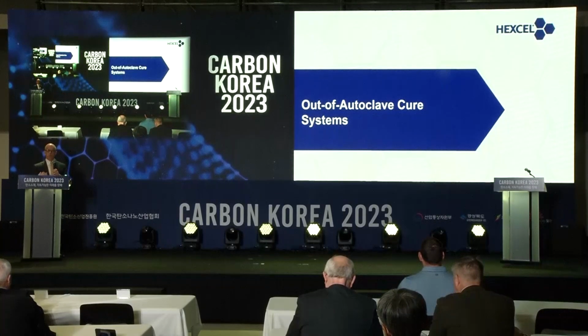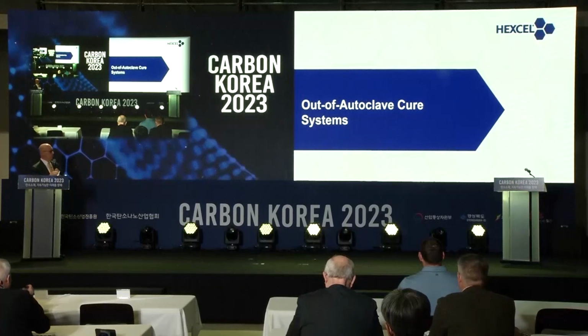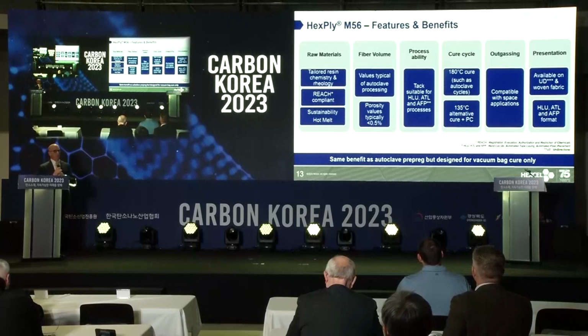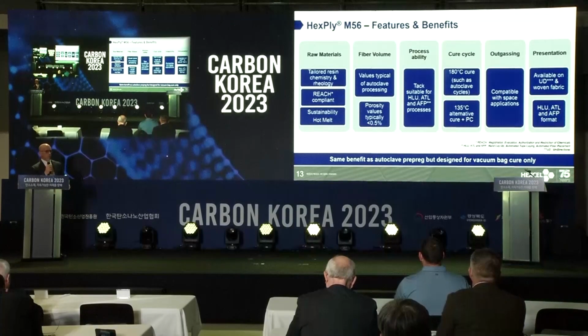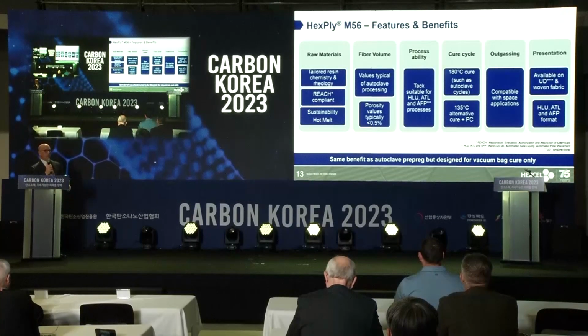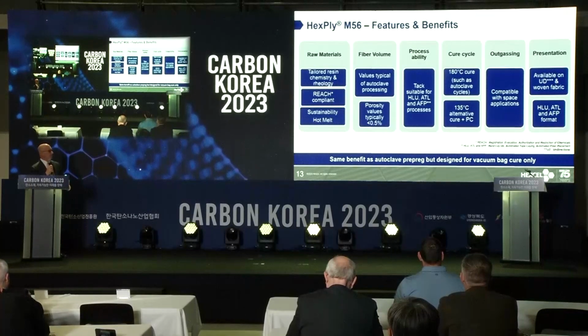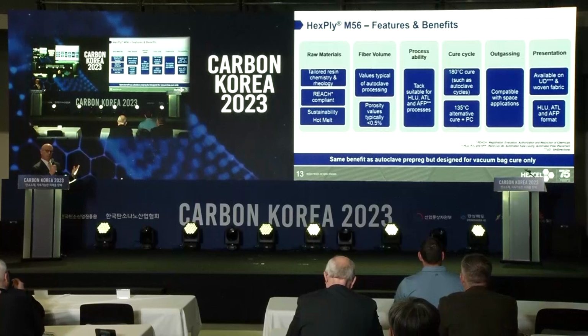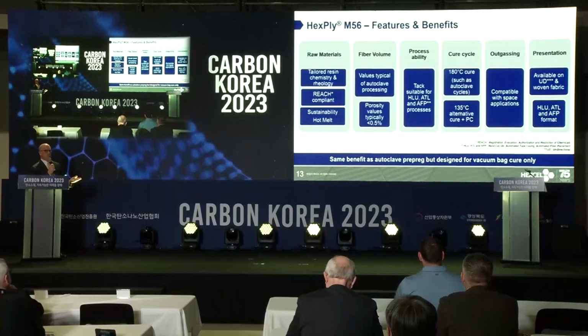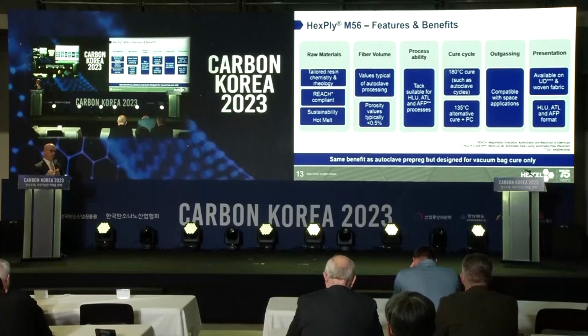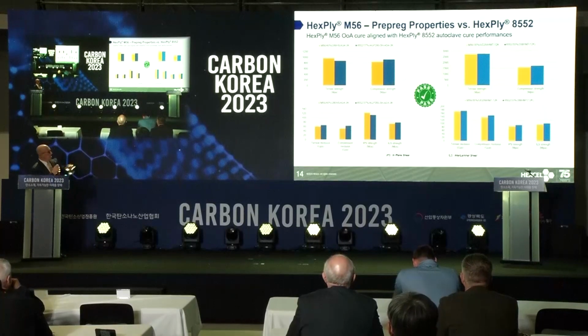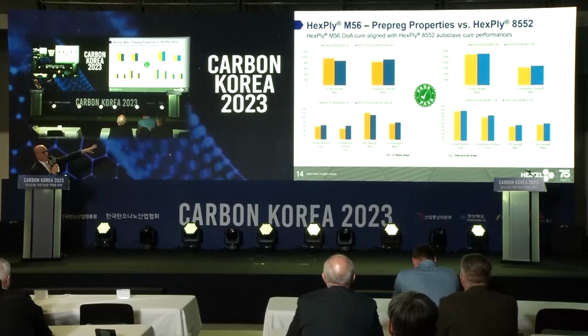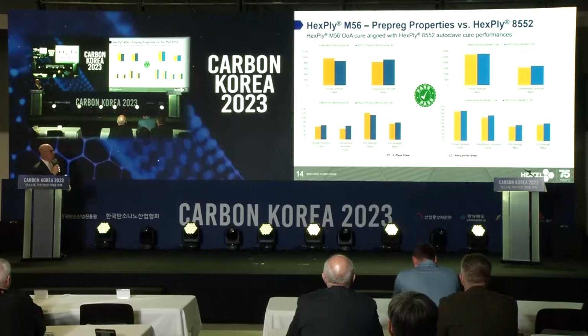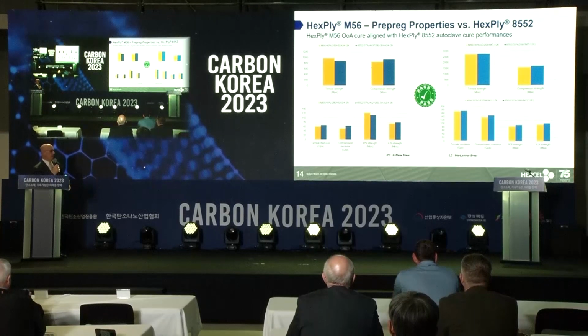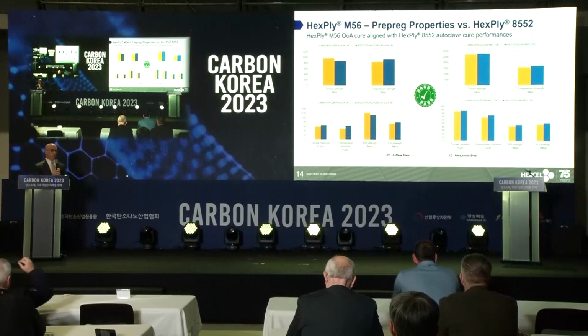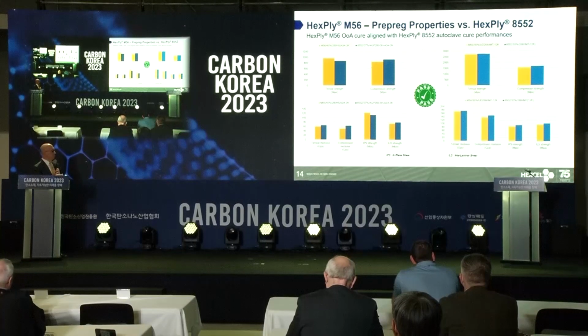Okay, but as I mentioned, the move towards the future is for out-of-autoclave systems, and so let me talk about a few of those that we've got. So M56 has been our out-of-autoclave solution for a few decades now. The material system performs well, it's been qualified, it's flying today, and it's a good system. Generally, it's slightly more expensive than the autoclave cure system, but you save the expense of autoclaves, and also the manufacturing is going to be less expensive. And when you compare material properties of M56 to 8552, they're fairly equivalent. You can see slight up or down between the two systems, but it is a good aerospace quality system that we've got good experience with.